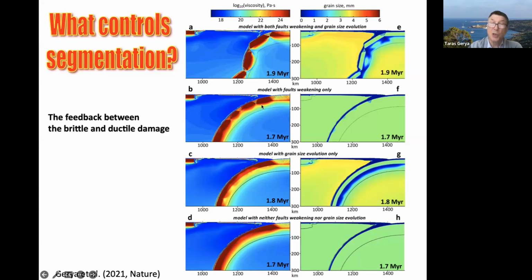So if there is no feedback from grain size reduction, so here grain size reduction was fully deactivated, then instead of segmentation, we see only shadows of this segmentation. So the length of segments does not seem to be very strongly changing, but the segments themselves are not very well evolved, and also large offset normal faults do not develop. Instead, more distributed faulting forms. So still we see that the main reason for this segmentation is coming from the strain weakening of faults at the surface. This is the master process, because if we deactivate strain weakening and leave grain size reduction, segmentation almost completely disappears. So we see this very uniform distribution. Still, there are some undulations, but they are not very well pronounced compared to this picture with fault weakening.